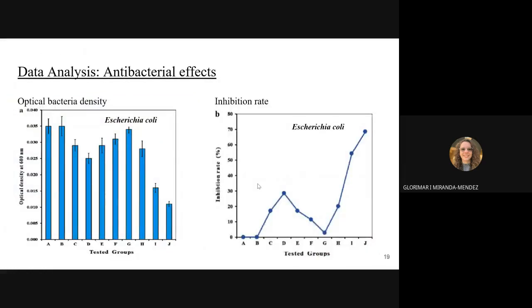And with the antibacterial data analysis, basically to determine the optical bacteria density, they suspend bacteria in saline solution and they take 0.9 milliliters and move it to a cell, and to that they add 0.1 milliliter for a total of 1 milliliter solution of nanoparticles, and they incubate that for 3 hours. Then they use UV at 600 nanometers to determine the optical density. So in a matter of how much the nanoparticles work as inhibition for bacterial growth, they obtain lower optical density.